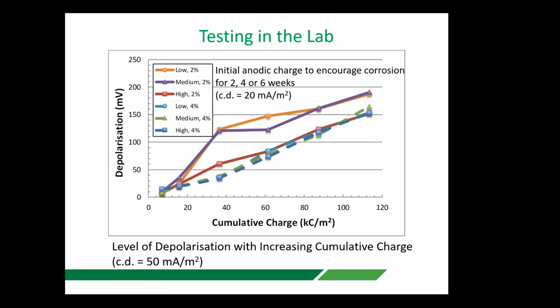Okay, what we found then by extending the experiments was the level of depolarization that was achieved. Now, bear in mind that the standard asks you to maintain a depolarization level of 100 millivolts when you apply a cathodic current, otherwise you're not complying to the standard. Now, we've pre-corroded these samples over 2, 4, or 6 weeks with an anodic current density of 20 milliamps per meter squared. And we also had various levels of chloride, 2% and 4%. The samples had corroded so much that even though we were applying more than double the amount of current density that we would normally apply for normal cathodic protection applications, it took a long while before we could achieve 100 millivolt depolarization. And in some cases, it needed a lot of initial charge to achieve that.